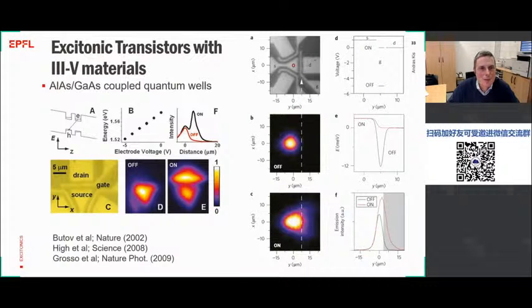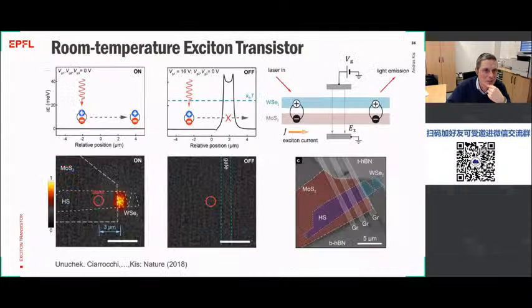But in 2D materials, excitons have a much higher binding energy, so they are much more strongly attracted, the electrons and holes are much more strongly attracted to each other, and it is possible to make transistors which work with excitons, but that can be operated at room temperatures. And this was the example that we had here. So using this approach of manipulating the exciton energy using vertical electric fields, in a heterostructure, we could switch on and off the current of excitons, and this you can see by looking at the emission coming from this spot at the heterostructure.